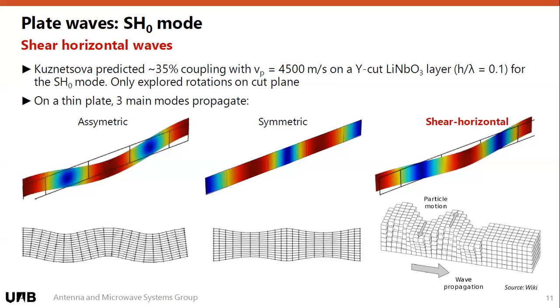These have also been called Love waves if you have an interface between a low velocity material and a high velocity material. But this is a wave in which the material vibrates in this direction and the wave propagates in that direction. I think this nice picture here allows you to see how the material will start vibrating. This is in contrast to what we call the SAW wave or the Rayleigh wave, which is a completely surface wave, in which the particles in the material describe an ellipse. A Rayleigh wave can only exist when the substrate material is really thick. If you go to thin layers, the Rayleigh wave cannot exist, and you only get these plate modes.